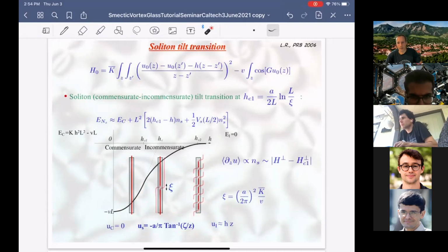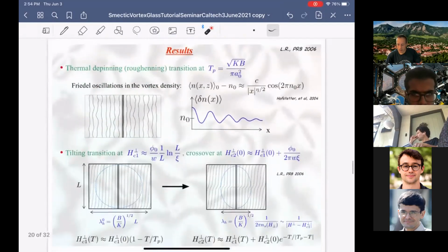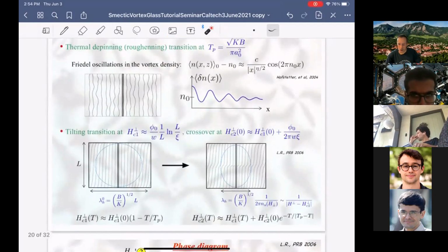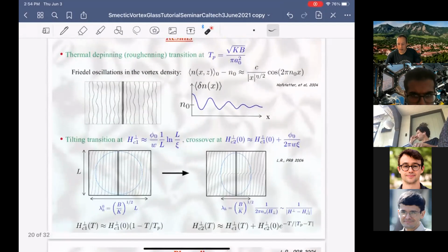And all that happens is as you apply bigger and bigger transverse field, you get more and more of these solitons. Eventually, those solitons overlap. So it's like the Sine-Hilbert analog of the commensurate-incommensurate Sine-Gordon transition that you're familiar with, now in this transverse direction. And here's the picture, and you can study this, and it looks like, actually without tilting, it looks like the Kane-Fisher impurity problem.